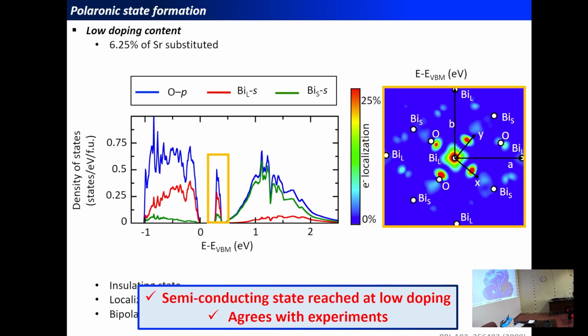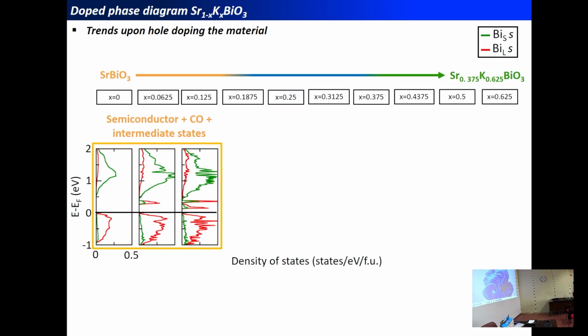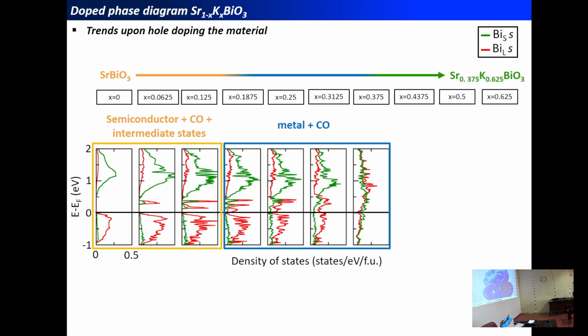So now we can try to go a bit further and put more and more holes in the system by substituting more and more strontium. If we do that, up to 12.5% of strontium substitution with potassium, we end up again with a semiconducting behavior with a small band gap and more unoccupied states, so we created more bipolaronic states in the material. If we continue to put more holes in the system, at some point the band gap closes in the material, but as you can see, between the density of states associated with the small bismuth cation and the large bismuth cation, there is still an asymmetry between the two types of density of states, meaning that there is still a charge ordering very likely in the material.